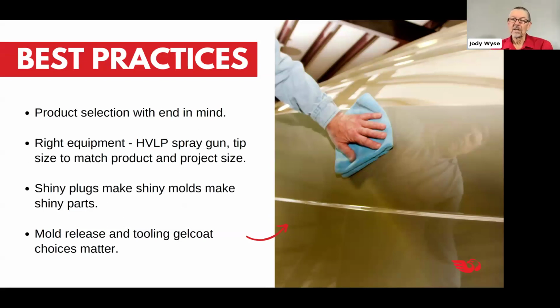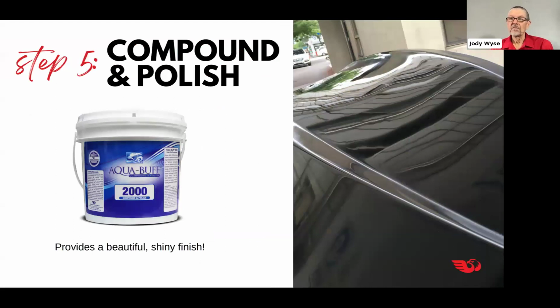And what we see in the tooling end of it is a lot of times they'll choose a sandpaper, and they'll choose a series of grits that they want to use to get to what they feel is going to be the right shine. But what they didn't know in the beginning was that first sandpaper that they used had left some marks in the surface, some swirls and some deep gouges, and they never sanded those out, and they're doing a 26-foot mold or something, and they finish with their final polishing and go, wow, we still see scratch marks. Now they have to start over again. You're better off doing a small area, and figure out what's going to work exactly right with the sandpaper you have, with the compound you have, with the buffers you have, what you're doing. Now you know the process on the rest of the part that will get you the desired result without having to rework things. Yeah. Fantastic.